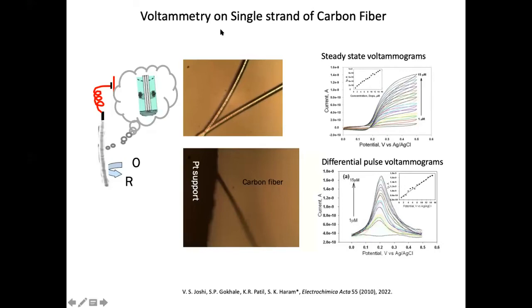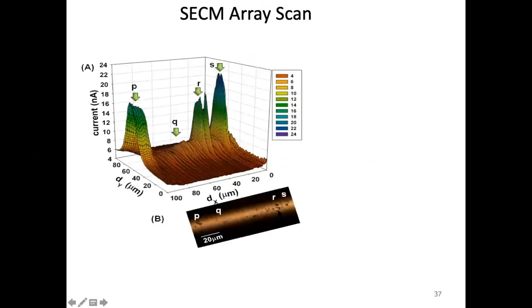When we looked under the microscope, we saw a lot of small black spots on this fiber. And we thought that those black spots are responsible for this catalytic activity. So we managed to measure the SECM on exactly the same portion of the fiber. And we found that where there are black spots, which I marked P, Q, R, and S, there is very strong electrochemical activity. That tells me that these black spots are more electrocatalytically active than the rest of the fiber.